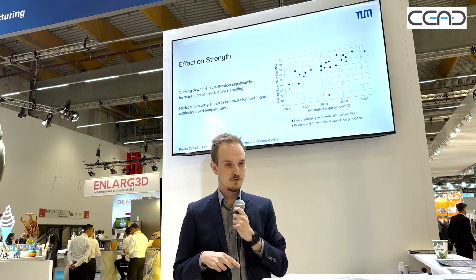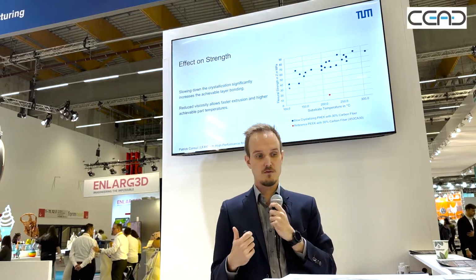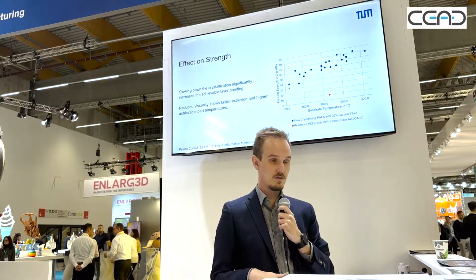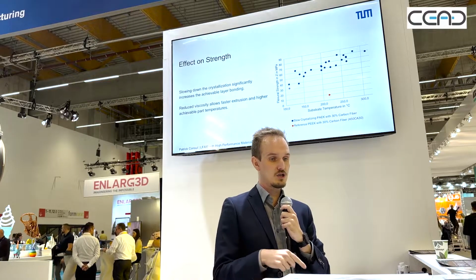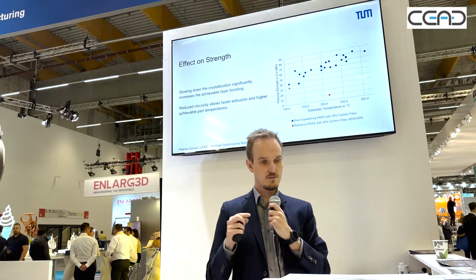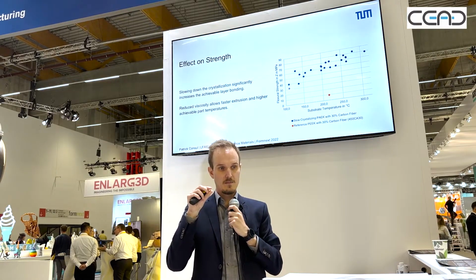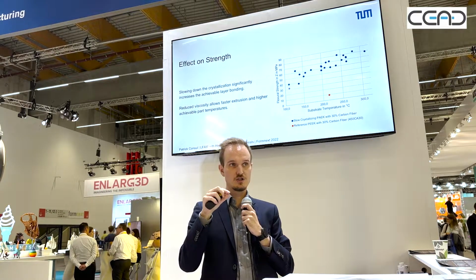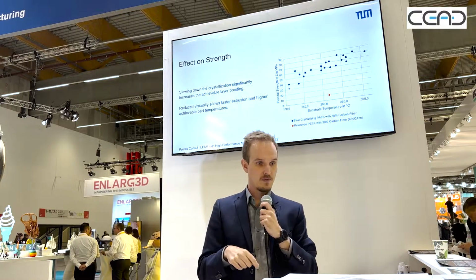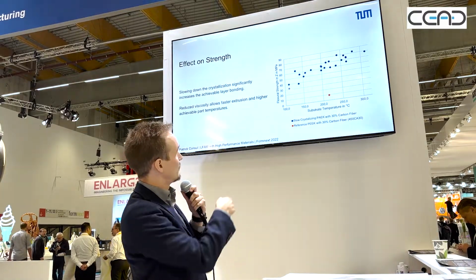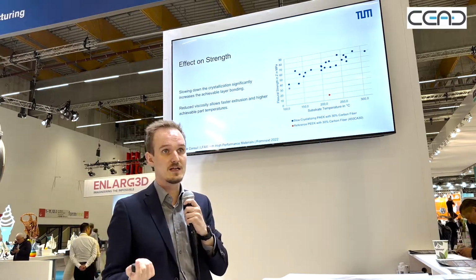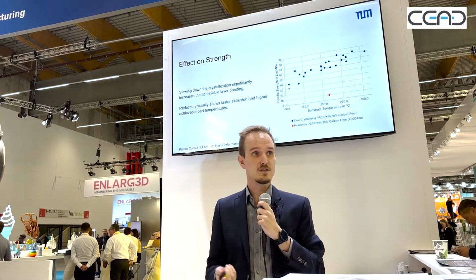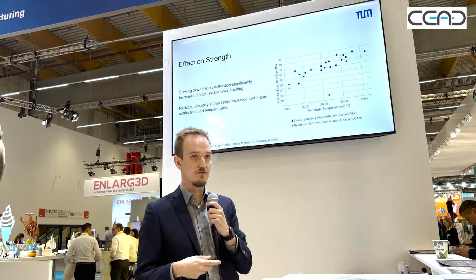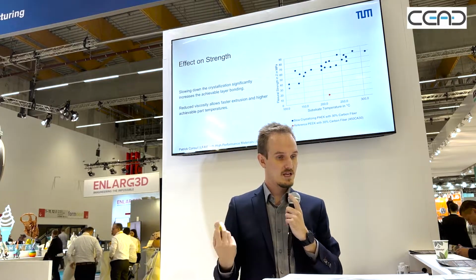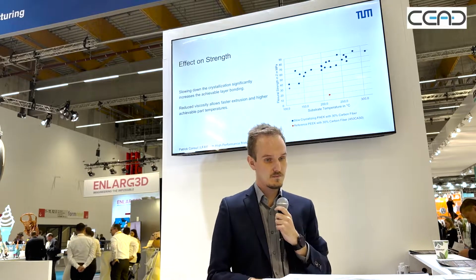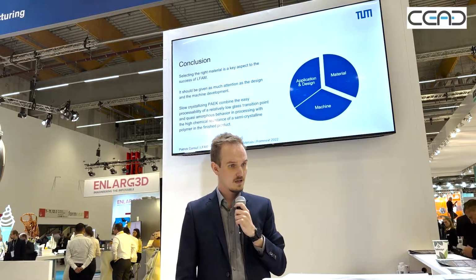But with these slow crystallizing polymers, you get, first of all, much higher strength at the same substrate temperature, but you also achieve better bonding at much lower substrate temperatures. So substrate temperature for me is the temperature of the layer just before the next layer is deposited on top. And you can actually see that even below 150 degrees Celsius, which is below the glass transition temperature for the substrate, you still get bonding which is much better than it would be for injection molded PAEK at over 200 degrees Celsius.